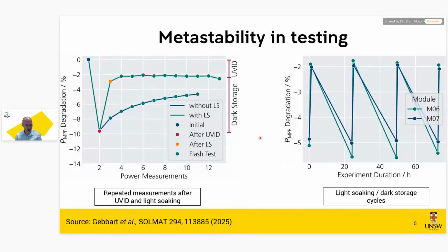This was work done by colleagues at Fraunhofer ISE, I think, where they showed that you can switch this metastability on and off by light soaking, putting the samples in the dark, light soaking, putting them in the dark. So again, an indication of metastability. And in this presentation, we will show you what the root cause of this metastability is.